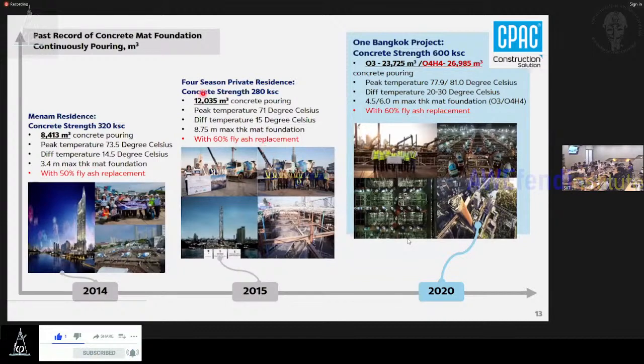And the next one is more challenging, but the strength is not higher, almost the same. Sorry, this one is in KSC, around 28 MPa. The volume of concrete becomes higher, 12,000 cubic meters, poured continuously, but the strength is not high. So it's not much of an issue, but we use fly ash at around 60% to replace the cementitious material. The interesting thing for this project is the thickness, which is quite high at 8.75 meters. This is the highest thickness of mat foundation that we have ever produced, but it's not a big area, just the core of the foundation.